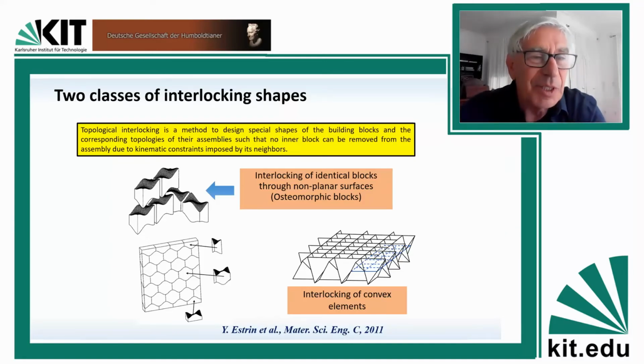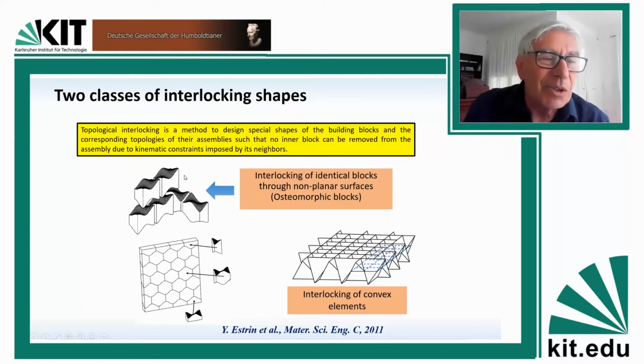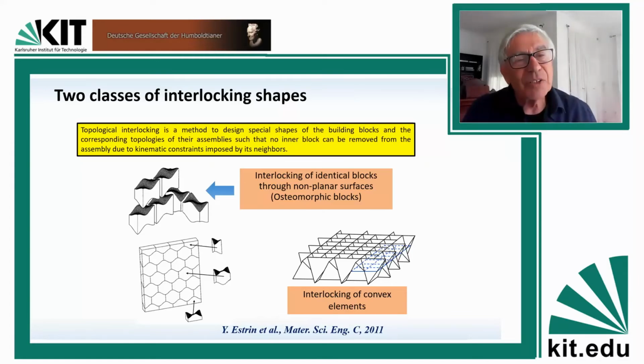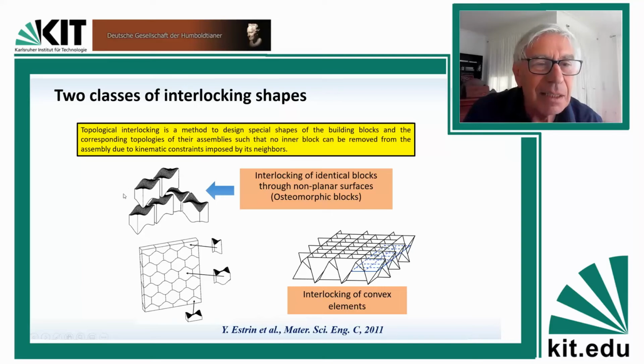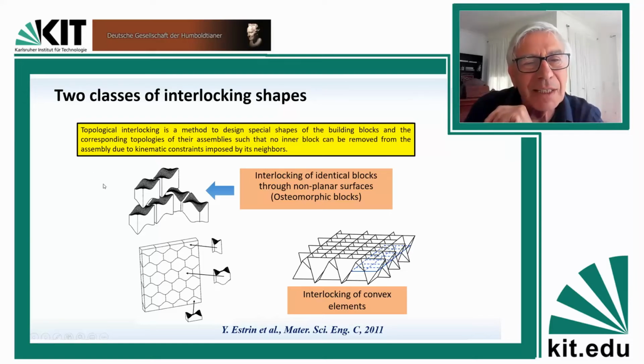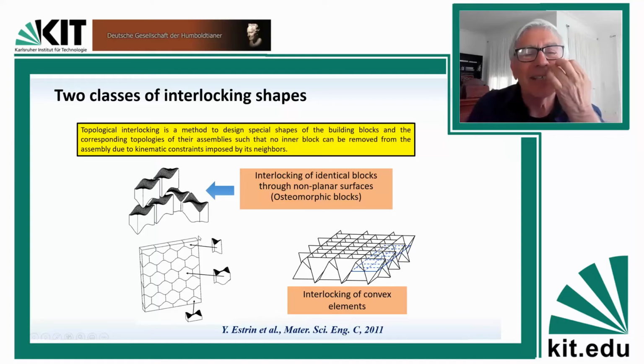Now, we want small elements, so we want to fragment or segment a structure into small elements, but we want to be able to assemble a structure from these elements. So we came up with a design which we called osteomorphic blocks, osteo from bone, obviously, and morphic relating to their structure. And these blocks have a shape which at the interfaces has concave or convex surfaces. If you match these surfaces in a way indicated here, you need a bit of geometric or space imagination to see what happens here. But you can see that you can produce a structure like that, a planar structure or a corner-like structure like that.